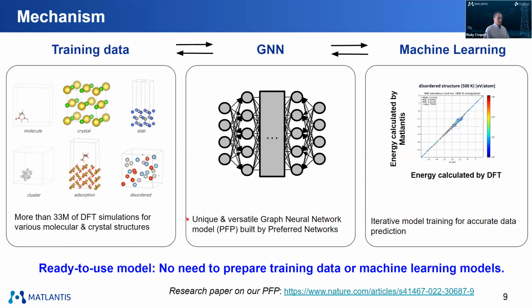We are relying on a graph neural network that was designed by Preferred Networks. We call this PFP, so Preferred Potential. And this is connected, of course, to machine learning. And with machine learning, we managed to achieve accuracy which is very good compared to DFT. You can actually plot the energy calculated by Matlantis against the energy calculated by DFT, and you find a very